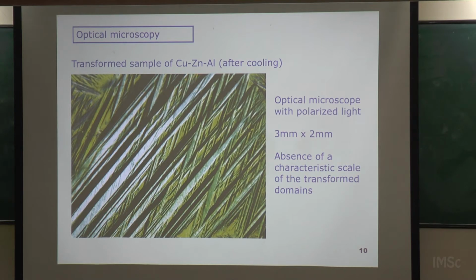Okay, so it's clear that the domains are elongated. These are what's called martensitic needles, but the typical length could be this one. But then you see others that are like this. Okay, and then you see others that are smaller. And if I magnify, I will see others that are smaller. There is no characteristic size for these needles. You have all the sizes coexisting, and when you do a statistical analysis, you see that you have few large ones and a lot of small ones. This is an indication that you could be facing a power law distribution of sizes, just looking at this picture, okay?